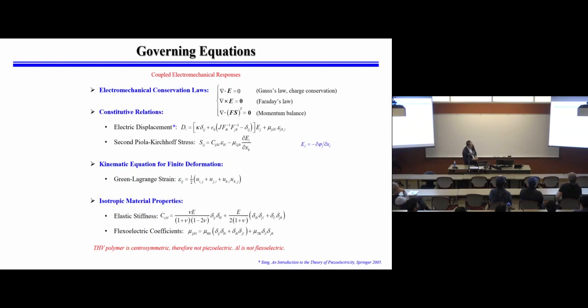So they are fully coupled. And then, of course, finite deformation, that's the Lagrangian strain that we continuum mechanics people are very familiar with. And then the elasticity constants, and then the flexoelectric fourth order tensor, you can see that they are very similar. Right? So we couple all that.